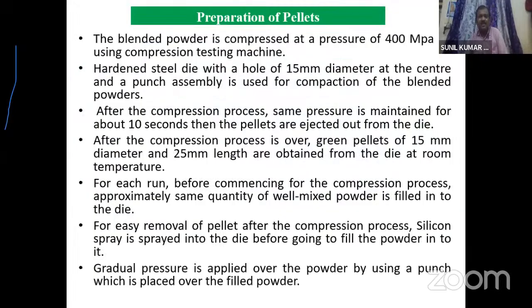Next, after blending, we are going to compact or press the powder by using a die set. Here the blended powder is compressed at a pressure of 400 MPa by using a compression testing machine. A hardened steel die with a hole of 15 mm diameter at the center and a punch assembly is used for compaction of the blended powders. After the compression process, the same pressure is maintained for about 10 seconds, then the pellets are ejected out from the die. Green pellets of 15 mm diameter and 25 mm length are obtained from the die at room temperature.